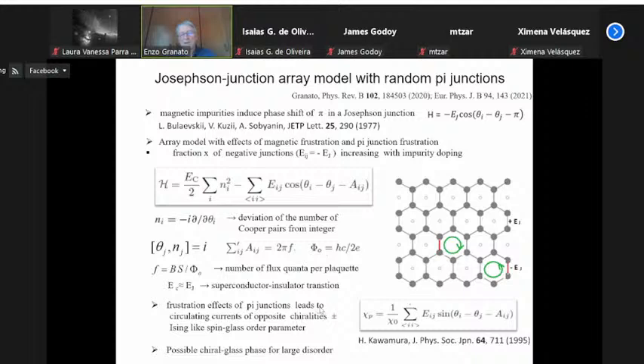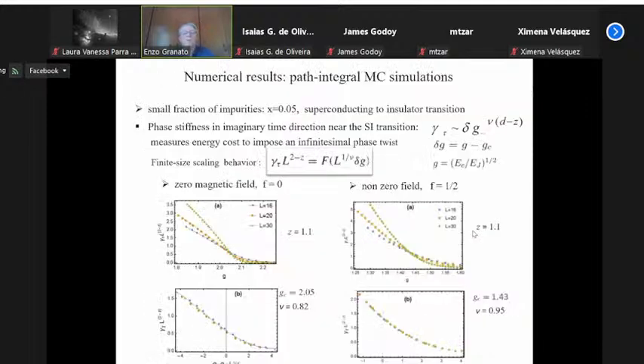This chirality can be defined as the circulating current around the loop, which is the sum of the currents of each junction, and the circulating current is induced by frustration. Kawamura studied the chiral glass in superconductors. But here is a case in which you have quantum fluctuations of the chiral glass. So the question arises whether there is a possible chiral glass phase for large disorder, and whether this chiral glass phase is a superconductor, an insulator, or something else, like an anomalous metal. So we performed calculations in this system, using quantum simulation again.